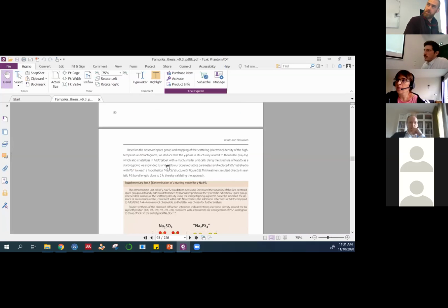The short answer is I simply didn't do it. The longer answer connects back to my comments before on how I think other methods are much better suited to understand this phase. My efforts right now are concentrated on, rather than small scale Rietveld models, trying to build big box models that I can populate with RMC, reverse Monte Carlo simulations, and then using that to fit both the pair distribution function and the Bragg diffractogram at the same time. In that way, instead of resorting to the Debye-Waller factors, which I criticized before, I can try to actually discretely point to the sodium distribution and the PS4 distribution, captured through averaging in a big box simulation.